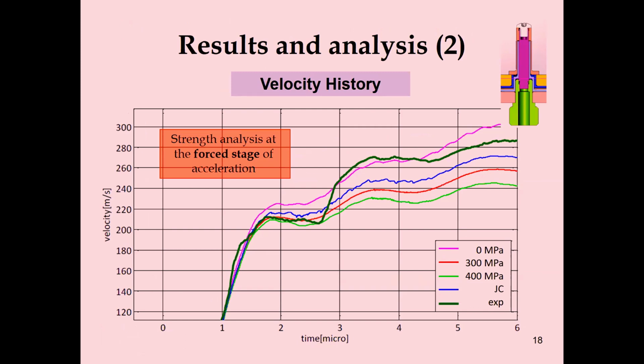So zooming in on this, again, we have those same slopes. It's just on a smaller period of time. Of course, this is not the way we calibrate it. We do it in a more rigorous and mathematical way, just to visualize what we're looking at. So we could do simulations with different strengths and calibrate a material model or the strength which fits the inclination which we're getting here on these experiments. I'll show in a minute the results we got for copper, and I could say it was accurate up to about 50 megapascals. So we could get a very good accuracy from this kind of analysis.